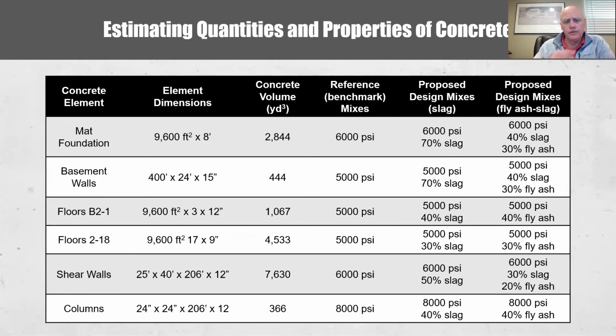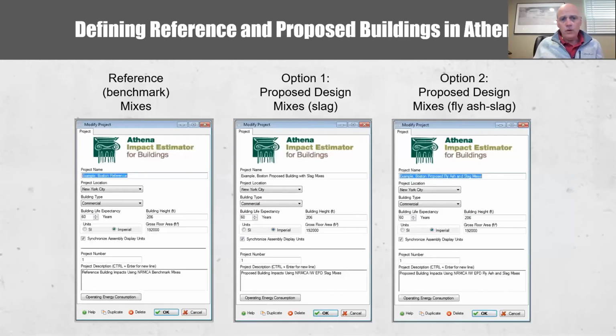And this is just a rough idea. Just focus on the last 2 columns. These are the proposed, last three columns, basically the reference benchmark mixes. And again, those are averages surveyed by us. Our members have reported back to us what the mixes are for those and the impacts are for those average mixes. And then the proposed mixes are different volumes of cement replacement or SCM content. And one, again, is just for slag, the other one is fly ash and slag. Running the program 3 times, you don't really need to do it 3 times. You could do it twice, once for the reference, once for the potential options. If you know that fly ash isn't plentiful in a region, you could just focus on slag and so forth, and vice versa.